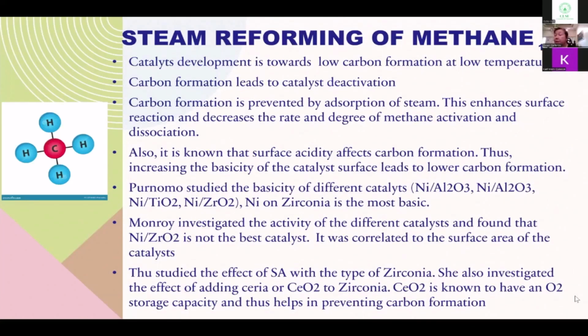For nickel catalysts, carbon formation is avoided when the concentration of carbon dissolved in the nickel crystal is smaller than at equilibrium. So, Rostrup-Nielsen in 2000 proposed that the steady state carbon activity could be decreased by enhancing the absorption of steam, enhancing the rate of surface reaction, and also decreasing the rate and degree of methane activation and dissociation. Noble metal catalysts were suggested as an alternative solution because these metals do not dissolve carbon. It is known that carbon deposition is favored on catalysts with strong acidity and weak basicity. The previous study conducted by our scholar in the laboratory proved that nickel and zirconia had the highest basicity among the 4 catalysts used.